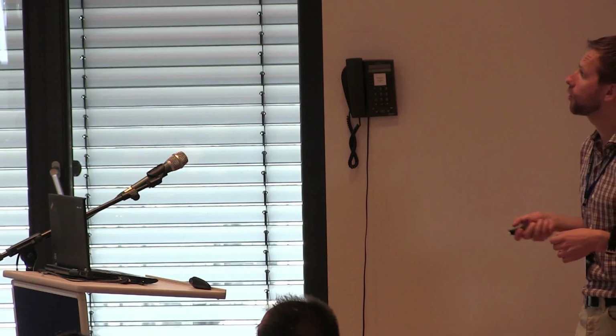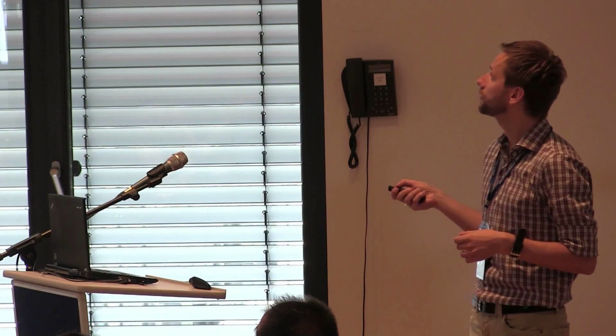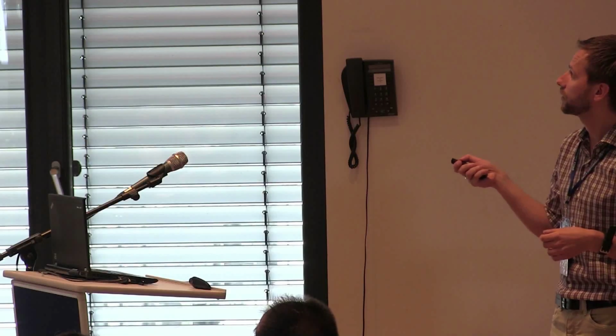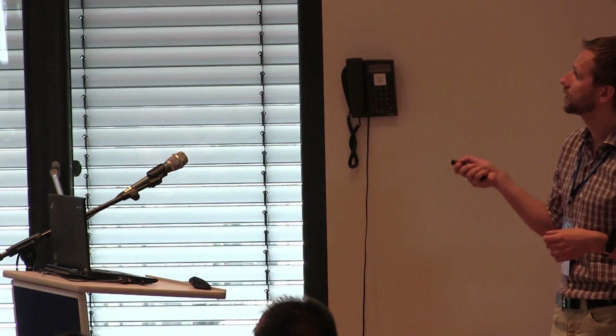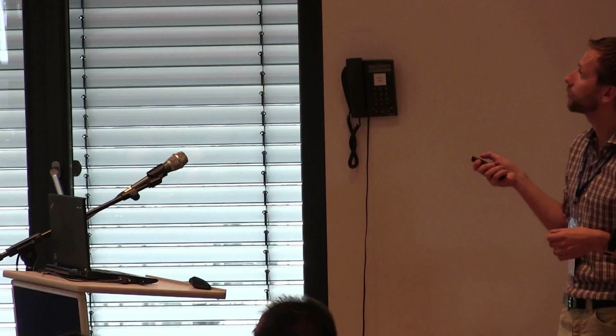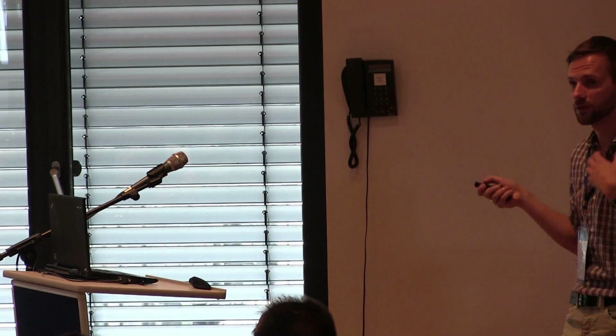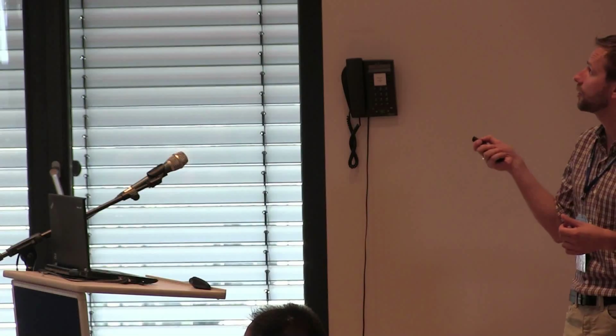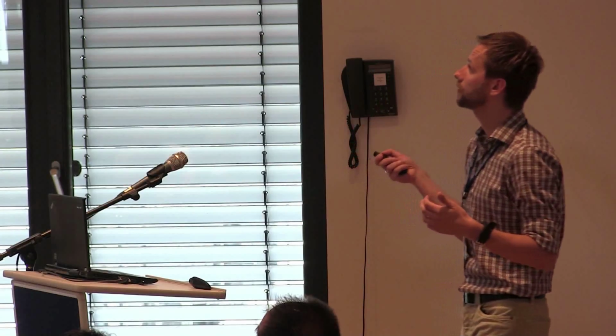So this is exactly what happens to graphene in Terahertz fields. Again, this is this famous Dirac cone, the linear dispersion of graphene. So the graphene is doped, this is the Fermi level, then you apply this electric field, and then you start depositing the energy into graphene by driving the currents by a conductivity mechanism. Real part of the conductivity is proportional to the power absorption. So this is how you deposit this extra energy to the Fermi sea of graphene.